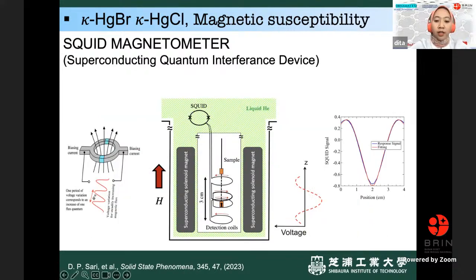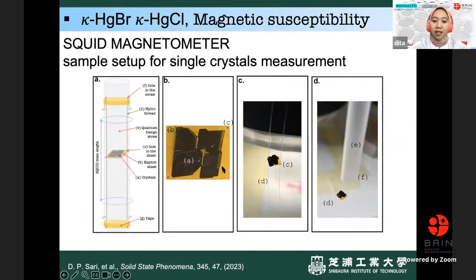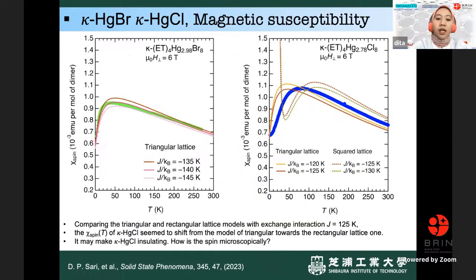The sample can be set like this. This is the single crystal that we put in the straw. Okay, so for the bromine, you can come back to the bromine and chlorine sample. So this is the typical curve. When we cool down the temperature, it will have a broad peak like this, and it is best fit by the triangular model. Yeah, it's as we expected.